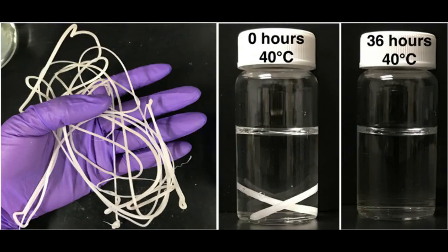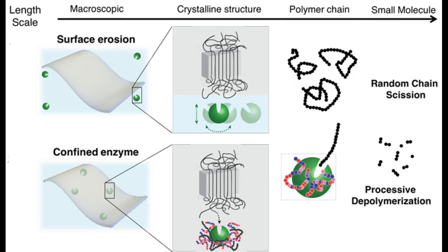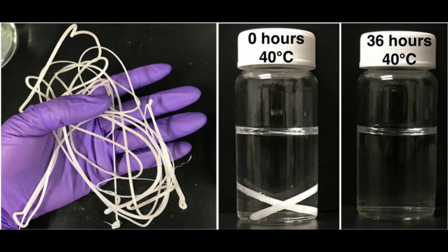For the research reported in the Nature paper, her team used a similar technique, enshrouding the enzyme in RHPs and embedding billions of these nanoparticles throughout plastic resin beads that are the starting point for all plastic manufacturing. She compares this process to embedding pigments in plastic to color them. The researchers showed that the RHP-shrouded enzymes did not change the character of the plastic, which could be melted and extruded into fibers like normal polyester plastic at temperatures around 170 degrees Celsius. To trigger degradation, it was necessary only to add water and a little heat.